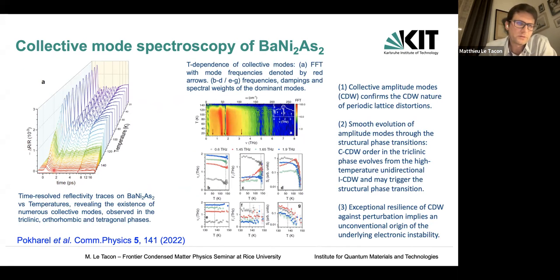Time-resolved reflectivity, sorry, to look at the collective excitation associated with the charge density wave. They measured it in the triclinic phase, but basically as a function of temperature, in the parent compound. This appeared earlier this year in Communications Physics. The bottom line is that what you see are collective amplitude modes of the I-CDW, which confirm that these periodic lattice distortions are really a charge density wave in nature.